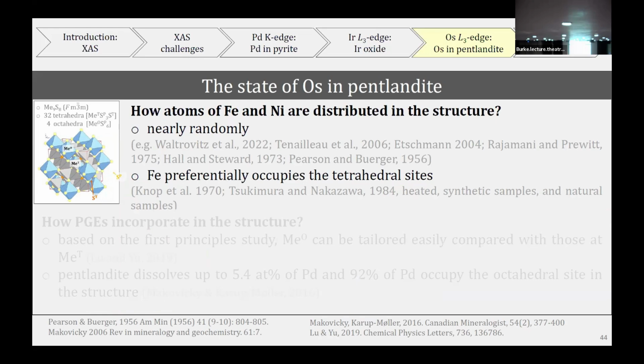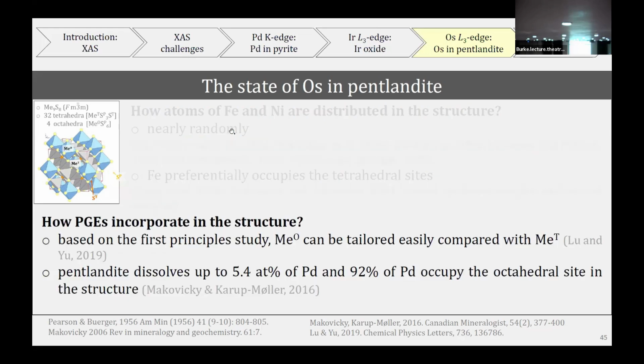So there are plenty of works devoted to the distribution of iron and nickel between the tetrahedral and octahedral positions. But in my opinion, maybe somebody would correct me, most of the papers state that they are nearly randomly distributed. So we didn't even try to distinguish between iron and nickel. And also, it's almost impossible by XAS because they have extremely close molar weights. Yeah, and there are not that many papers on how platinum group elements incorporate in the structure.